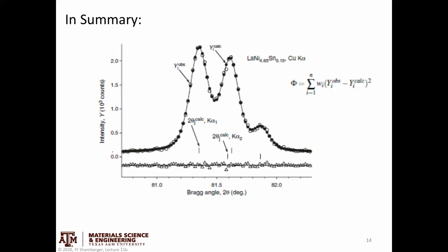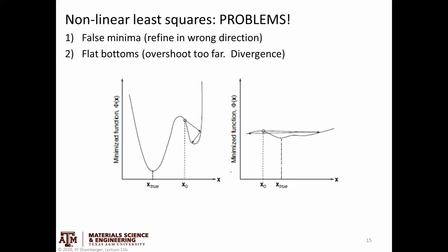When you do all these things correctly, the model in black points almost exactly overlaps the observed data in white circles, and the difference curve is very flat all the way across the peak. If the difference curve is not flat, that's indicative of which parameters you probably need to go back and improve.